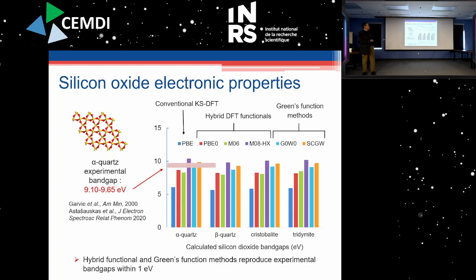Again, we can work harder to get the electronic properties for silicon oxides that come close to or agree with experimental data. If you look at the band gap for quartz silicon oxide, that's where it is experimentally. And if we use conventional DFT, we severely underestimate the band gap, but working harder with those Green's function methods, or hybrid DFT, which comes at a lower cost than those Green's function methods, but still a much higher cost than conventional DFT, we're able to find band gaps within 1 electron volt. Okay, so we know the limitations of our calculations that way.